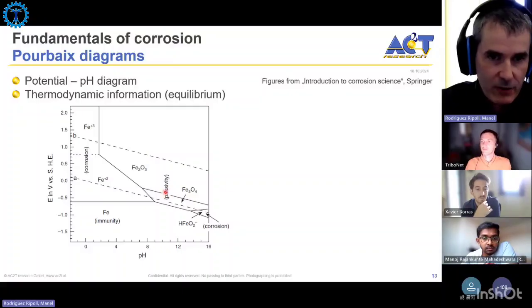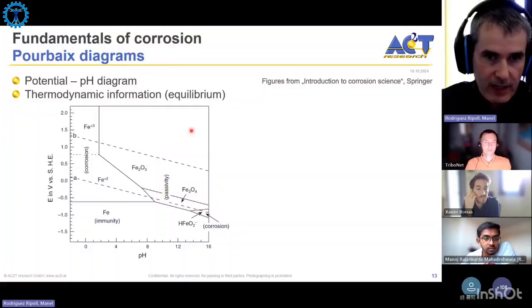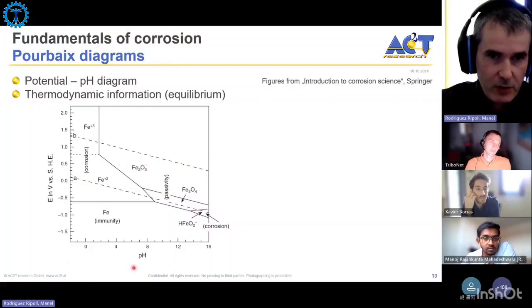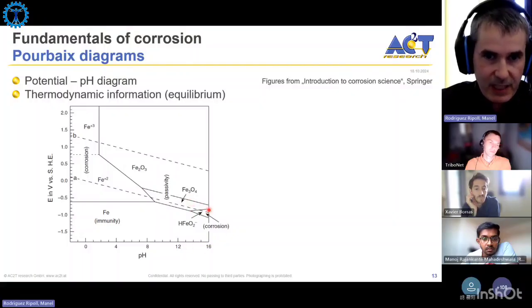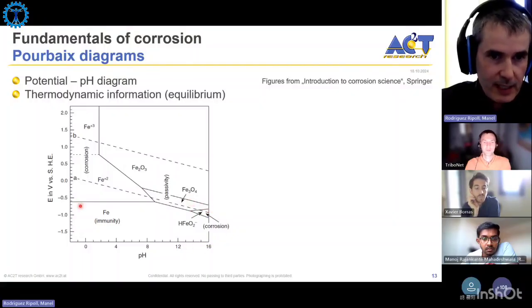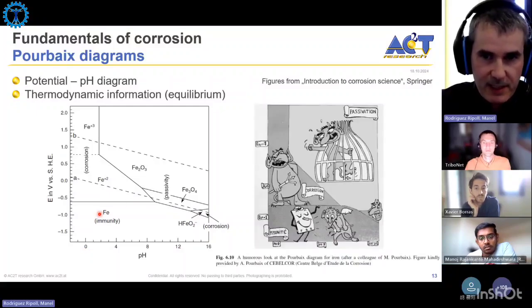For example, if we have iron, in this domain we will have passivity. So here at moderate pH we will have the formation of Fe2O3. Here at lower potentials and higher pH we will have Fe3O4. Here we will have corrosion at very high pH. Here, under cathodic protection, we have immunity. And we can have this representative way.